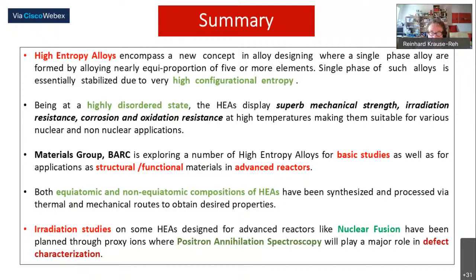See, in the fusion reactor, we have avoided niobium. If you see, we have gone for tungsten and vanadium based alloys. Niobium alloys were basically explored because by adding niobium, you can retain some ductility in the material, which is generally not possible if you are adding too much tungsten and vanadium based alloys. So that is where some compromise was made, but we do have one alloy system where niobium is not there at all. I think one of the last ones I showed did not have niobium. Okay, so there's a chance to avoid these very long half-life isotopes. Yeah.